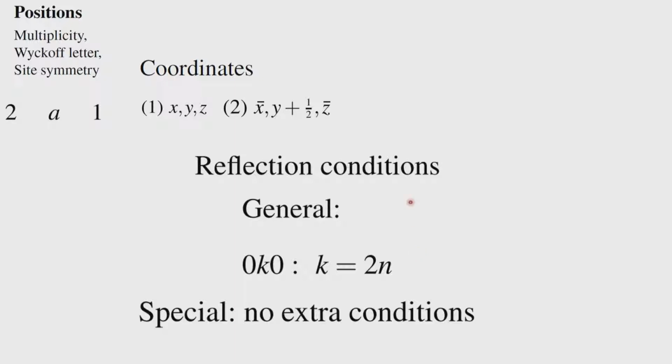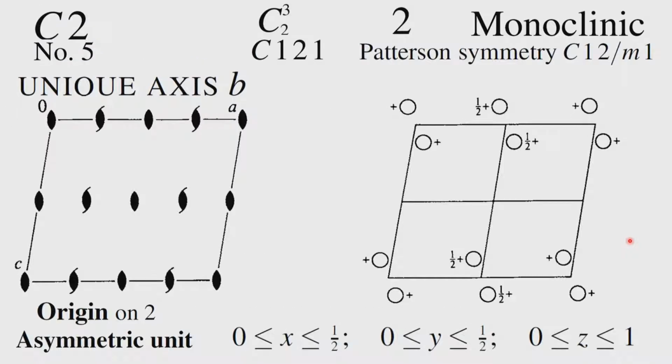But for all practical purposes, if we have a P21 symmetry for our current discussion, 0k0, k odd will be absent. So, we identify the axial absence and determine the space group uniquely. So, it is P21 system which can be uniquely determined. Next we go to the case where we have a centering.